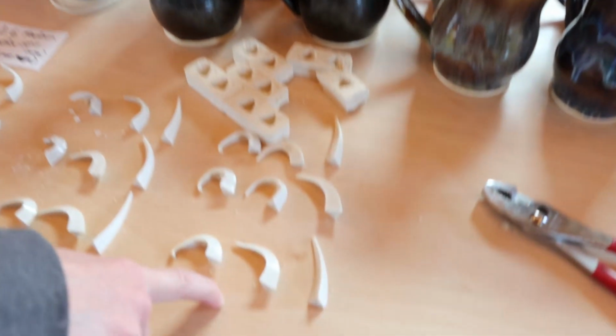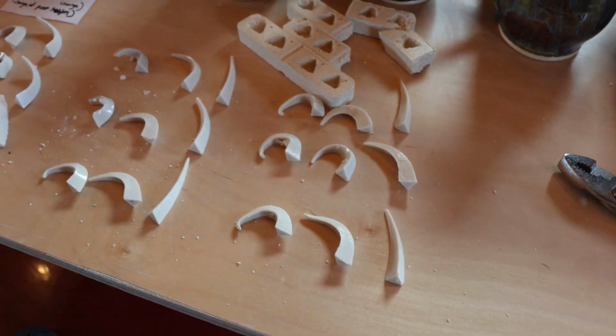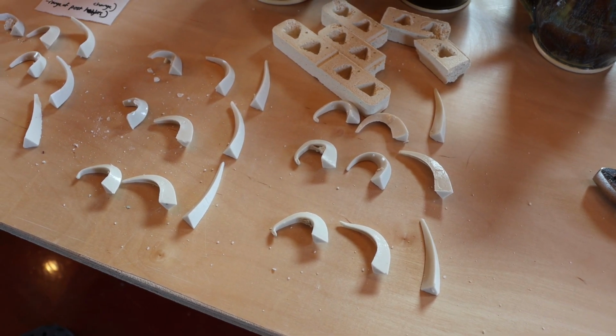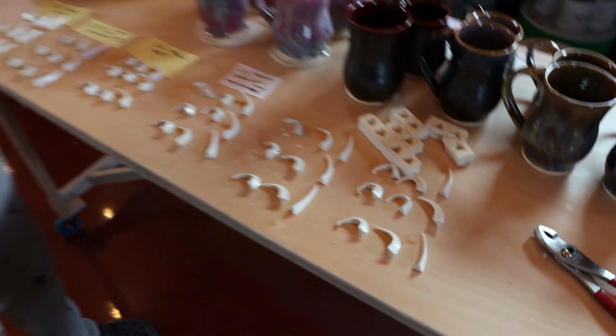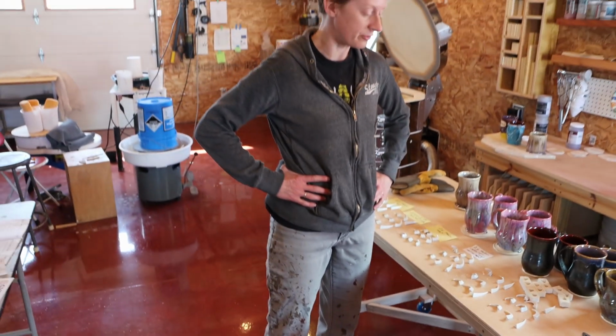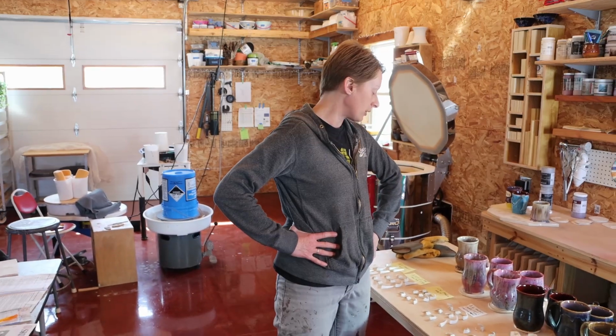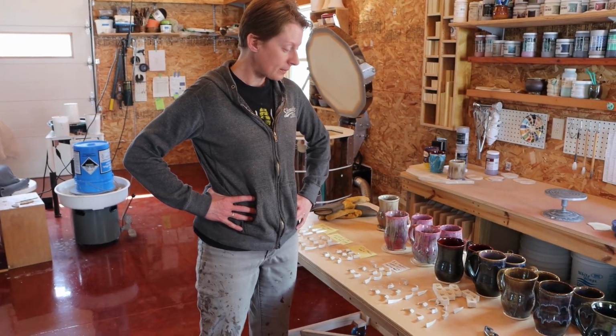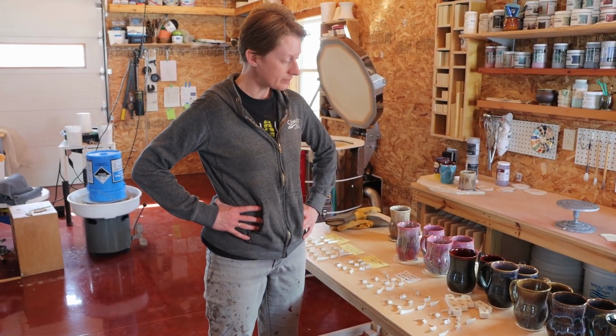And then this was the latest firing. It was a more full kiln with just regular glazed pieces, and it was still using the cone 6 with the 10 degree offset, so cooler than 2232 degrees. It was the same parameter settings as the last one, we just had more pottery in it.